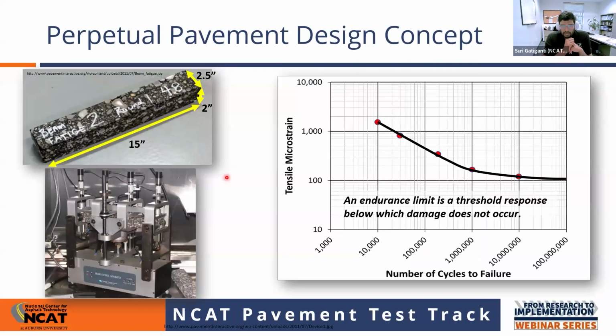For some of you that know a lot about asphalt mixture testing, if you see the bending beam testing, right? The bending beam testing is basically a strain control test. And as we decrease the strain level that we're applying on the beam, we start seeing increased life, right? Because once we start reducing the strain that we're putting on the beam, we are basically allowing that beam to sustain for a longer time. And for any material, there is something called an endurance limit. Basically, if you are applying a strain value below that endurance limit, that material is going to last for infinite life. What it means is if you're applying a strain level below that endurance limit, you're basically not causing any fatigue cracking or any fatigue damage of that material.